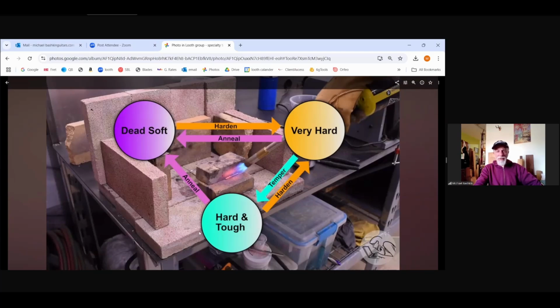So the tempering can be done a couple different ways. I opted to use just a toaster oven, but you can also do it with a propane torch. There's a little bit more finesse involved, but it's very quick. In the toaster oven, you need to let it go for about an hour, whereas with a propane torch, which I'll talk about in a minute, you could do it in probably less than a minute. So, all right, let me move this over here. I'll go to the next slide.